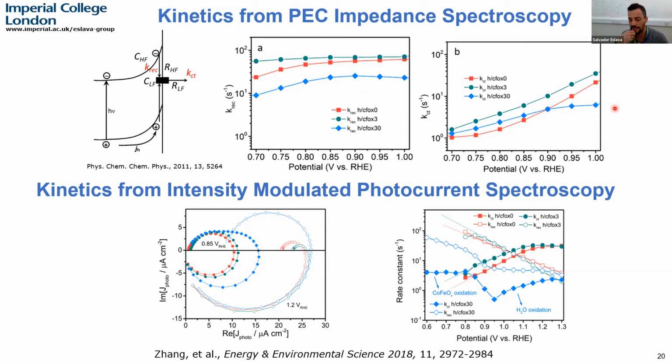What we want is a transfer, because we want to have more oxygen evolution. And this increased charge transfer is achieved when you limit the amount of the electrocatalyst. So we don't have to care so much about the recombination rates, which are often very discussed in literature. It's more important the charge transfer rate, at least in this case, in which we see that we can have some problems of dark currents.